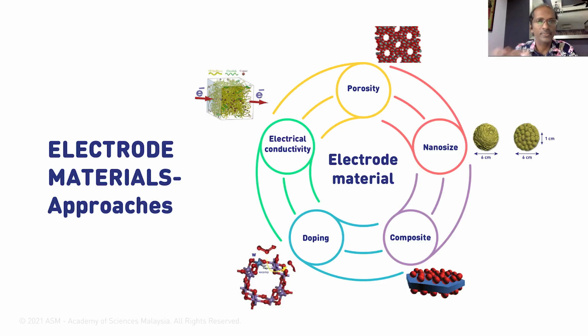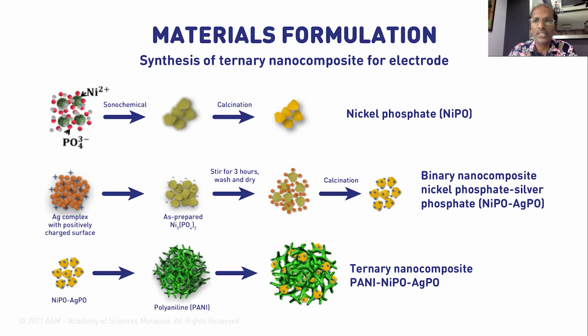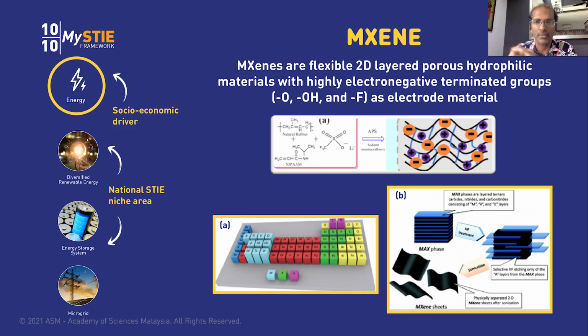used in device. Next, I'm also sharing with you all the synthesis of ternary nanocomposites as an electrode material. By itself, one material may not express optimum characteristics. So here we combine three compounds, which gives the best characteristic material to be used as electrode. In this case, we use a combination of nickel phosphate, silver phosphate, and polyaniline. Results clearly show that ternary composite-based devices show better performance compared to binary nanocomposite and nickel phosphate based devices.